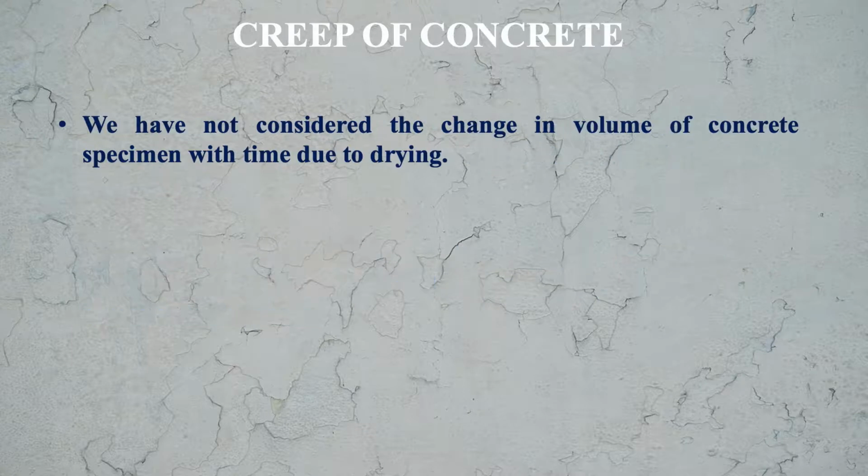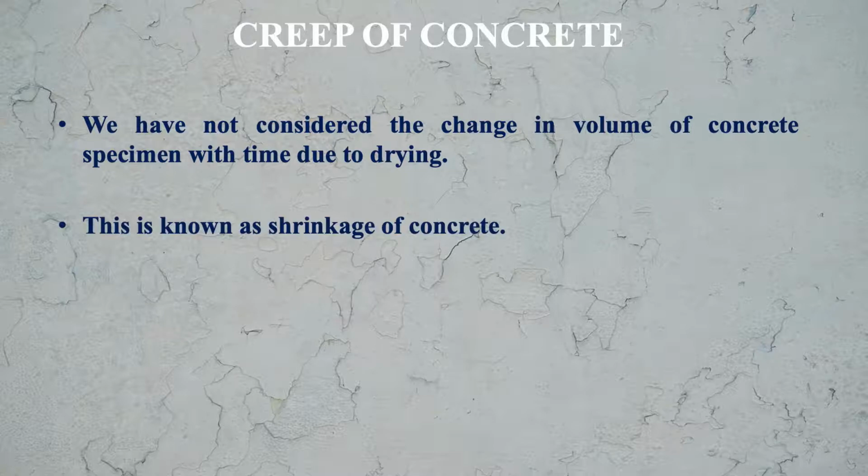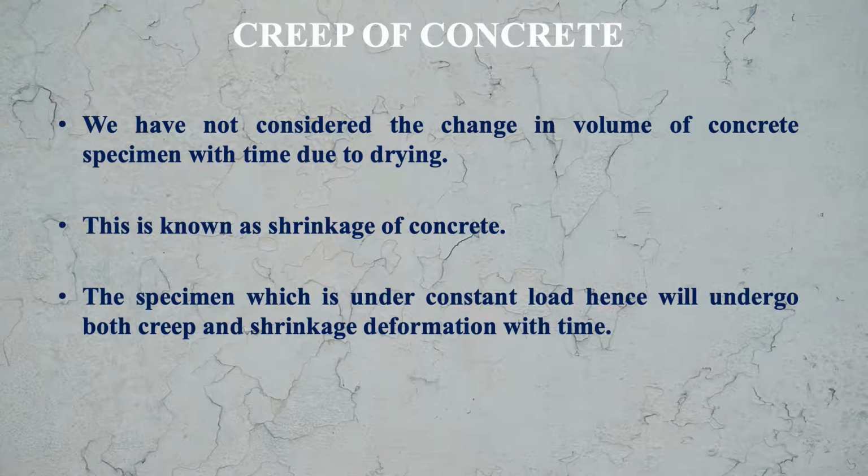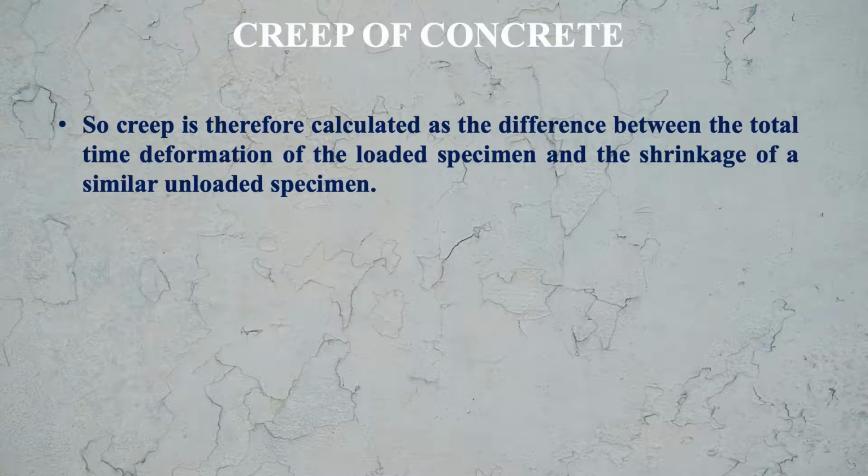We have not considered the change in volume of concrete specimen with time due to drying. This is known as shrinkage of concrete. The specimen which is under constant load hence will undergo both creep and shrinkage deformation with time. So creep is therefore calculated as the difference between the total time deformation of the loaded specimen and the shrinkage of a similar unloaded specimen.